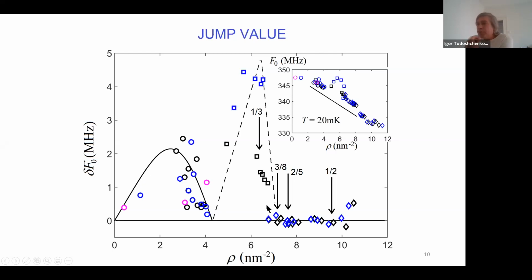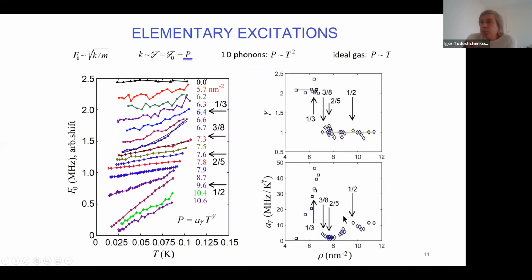In the solid, we have the largest jump, corresponding to the largest additional stiffness produced by helium at exactly 1/3 coverage. And exactly when we enter the dimer solid, immediately we see the drop of this jump value, which means that there is no additional stiffness produced by this phase. Okay, this was about mechanical properties of helium.